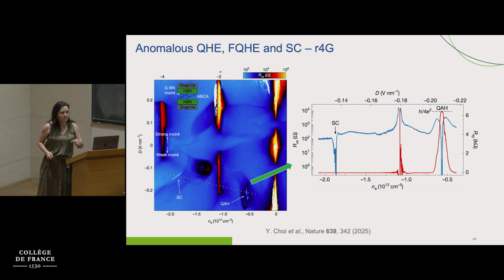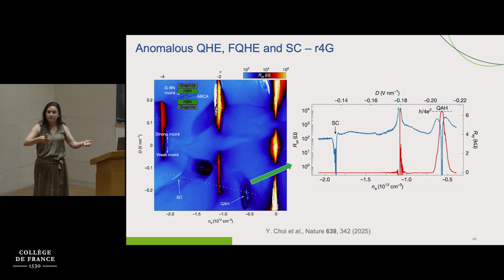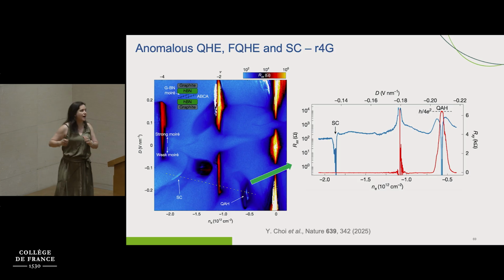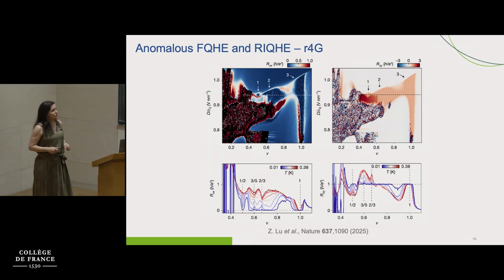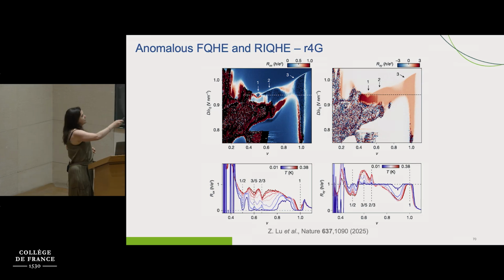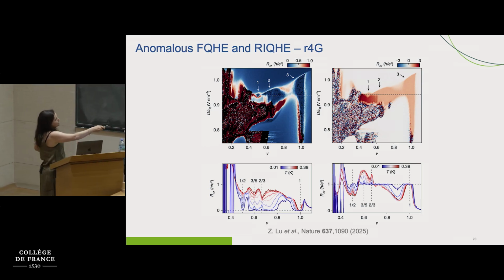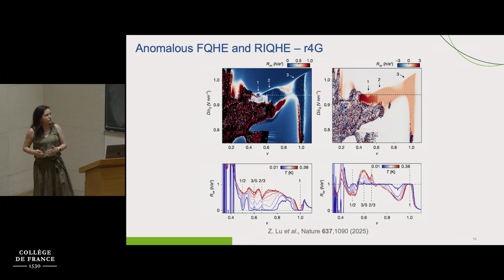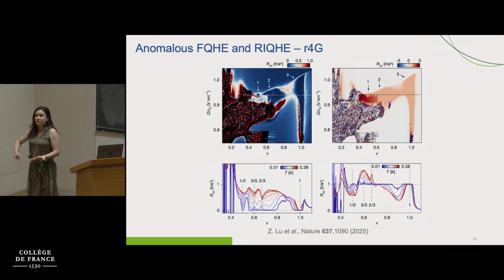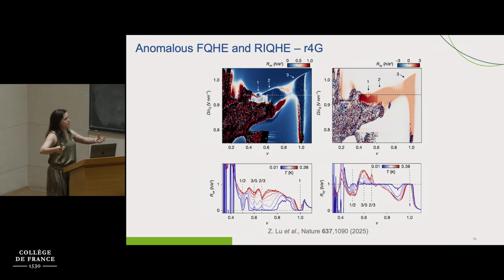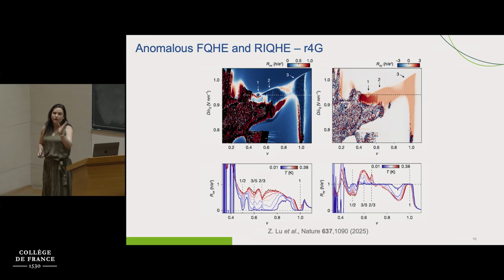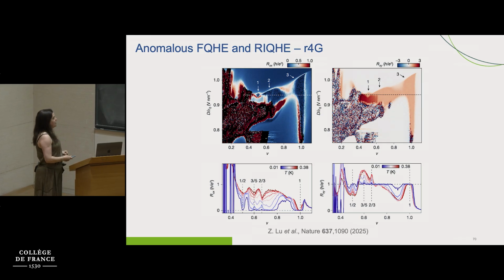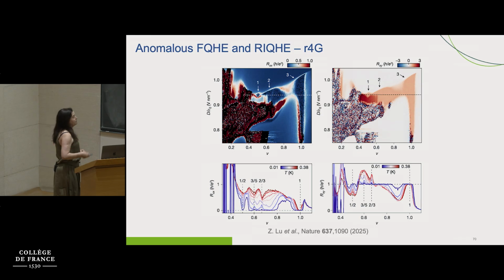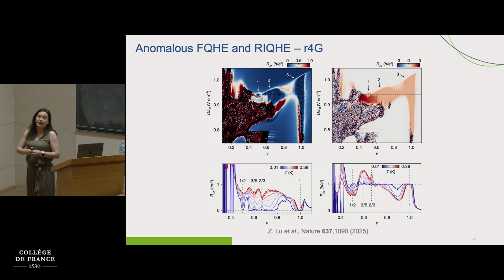Now, the other thing that you haven't seen yet is the electron solid, no? At the beginning, we were talking about integer quantum Hall effect and fractional quantum Hall effect. Keep increasing your interactions, you're going to have an electron solid. Well, it turns out that you can also have an electron solid without magnetic field. So nowadays, with these incredibly clean samples, you can see the reentrance of the integer quantum Hall effect at very low temperatures, but without any magnetic field. This means that the interactions become higher and higher, and then your system is going to organize as it did before. Whether this is a bubble or a striped phase is still under debate, but there are very recent developments by the Xia group, by the Lee group in Texas that show that this might be a bubble phase.